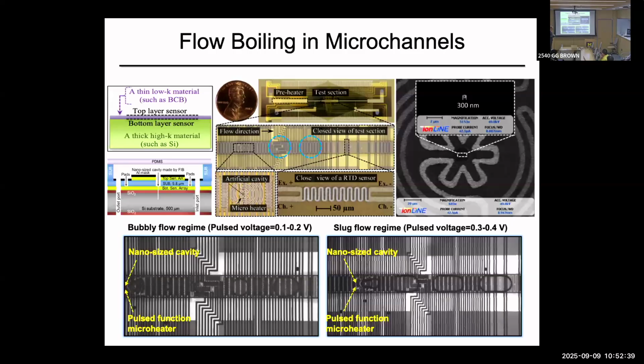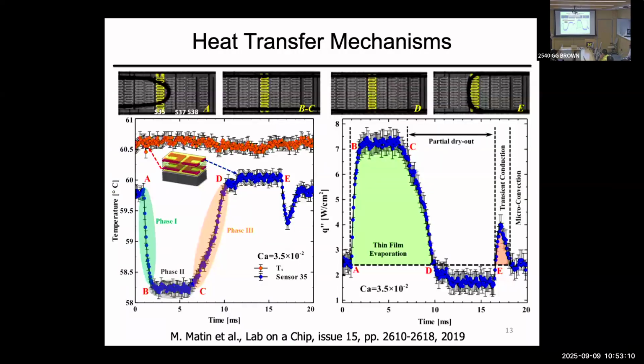So basically you could apply a pulse in this artificial cavity with the heater, and you can produce bubbles. And as they move, you synchronize images and the data, and you can read the heat flux at any part of the surface. You could manipulate this voltage such that you get larger bubbles, and you can produce essentially elongated bubble flow. We produced wavy annular flow and different regimes, based on the different heat flux and mass flux that we have. And you have a sequence of sensors on this side. Yes, exactly, 50. We collect more than about 1 million data points per second.